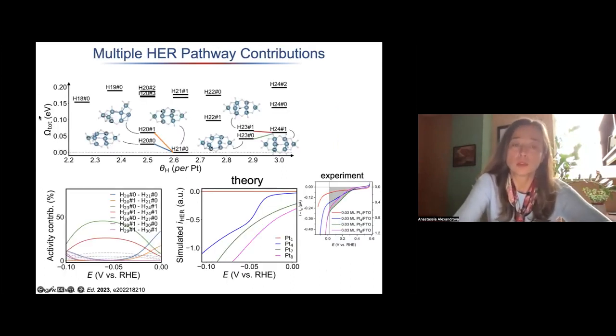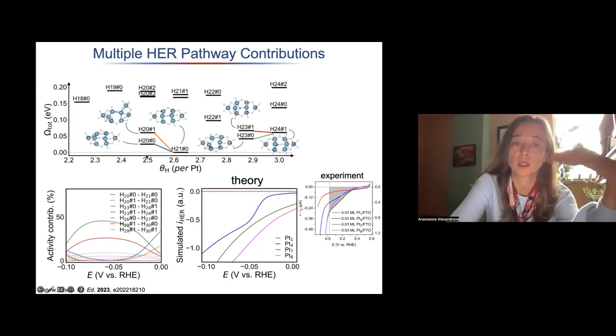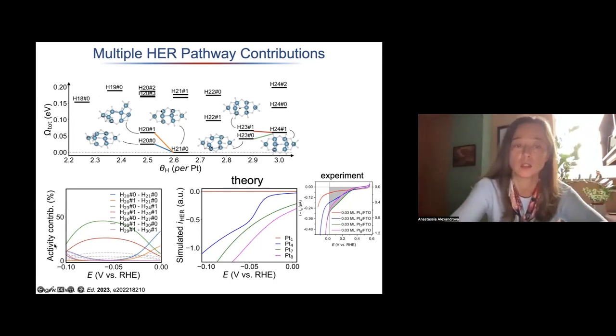And what I want to show you is a couple of things. So first, you see platinum with hydrogen, and I'll remove the support for simplicity, but these are supported clusters. These numbers, H18, for example, is the coverage. And these are various isomers that are accessible. So vertically, they are all on the same footing. Okay, grand canonical free energies, all these isomers are compared. They have different structures and different hydrogen coverages. And then we connect neighboring coverages and create the model for reactivity in HER.